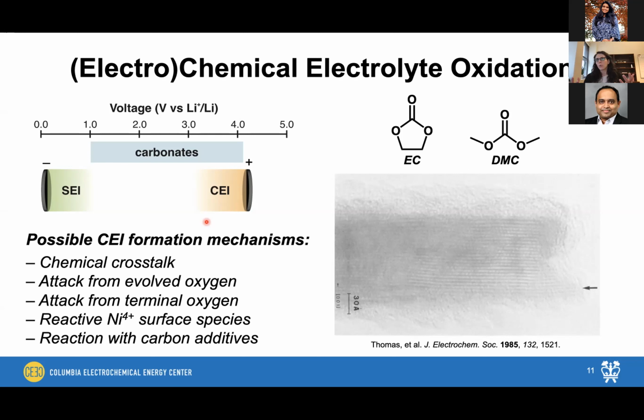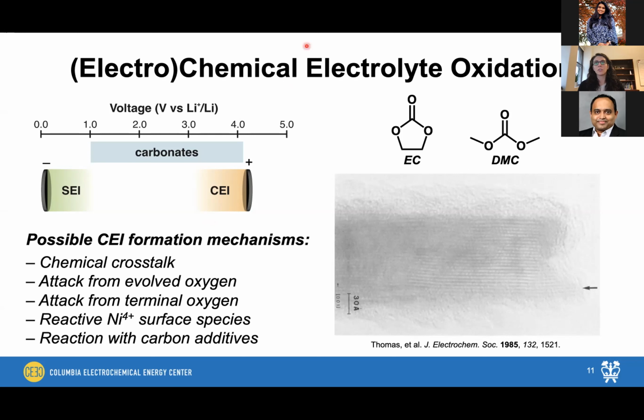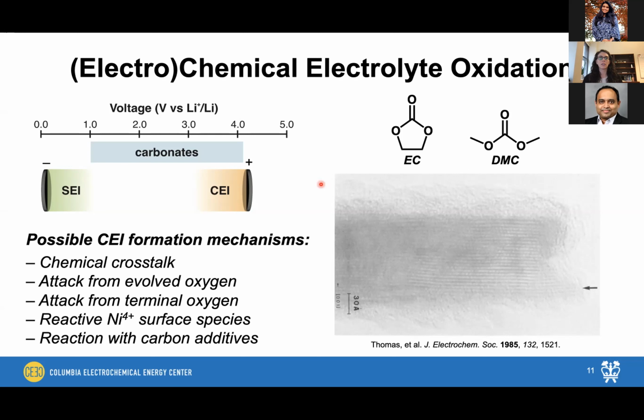And of course, as we're incorporating more nickel into our active particles, things like nickel 4+ on the surface of the material can also lead to decomposition of the electrolyte solvent itself. And then, of course, I also showed you this SEM of the cathode composite. And we also not only have to be worried about the reactivity of our active particles, but we also see that we have those carbon additives there. So it's also possible that things like our conductive carbon and our PVDF could interact with our electrolyte as well. So we have multiple components here that can interact with our liquid electrolyte and possibly contribute to interface formation on the cathode side of the battery.